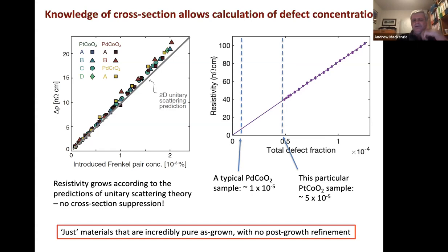So these are not topologically protected, at least not strongly. They are, in inverted commas, just materials that grow incredibly pure as grown with no post-growth refinement. But that's a kind of amazing thing, because when you were doing it in semiconductors, you did 30 years worth of material improvement. To get to these mean free paths in graphene took developments of very ingenious sample mounting and encapsulation techniques that took about 10 years to develop. Embarrassingly, we've done nothing to improve these crystals. We grow them by liquid or vapor transport methods, and they come out of the tube as good as this, and we really don't understand why.